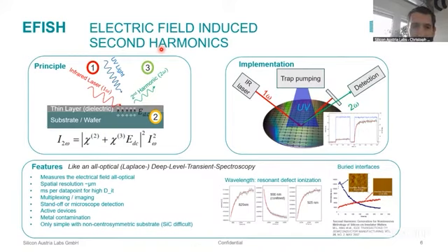So for instance, historically speaking, the silicon oxide interface, the big breakthrough before silicon semiconductors took off, was to have the passivation of the silicon, which led to a super good surface quality. So without a good interface, we would not have silicon integrated circuits today. But still, with new materials, it's always a topic to have good interface quality on nanoscales, but also for large areas, let's say for silicon carbide MOSFETs, because, well, you get tunneling, you get leakage currents, and you have to control this to get good device performance. So interfaces and interface quality is always extremely critical.